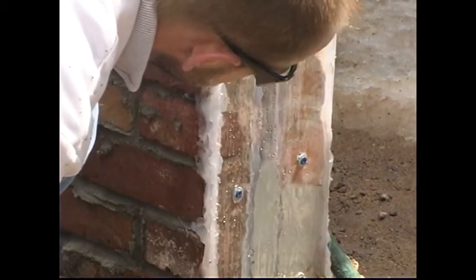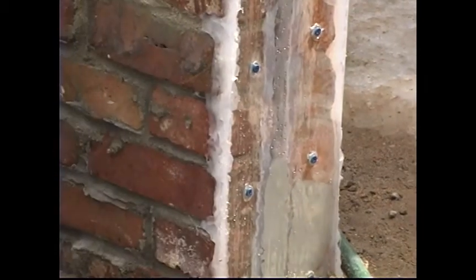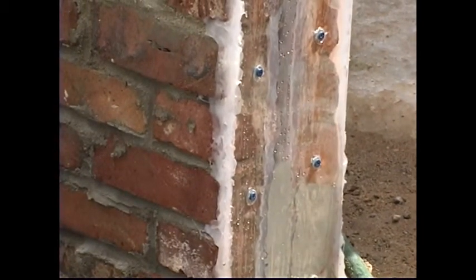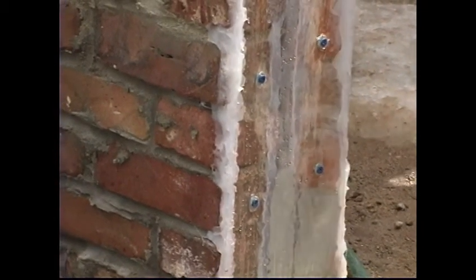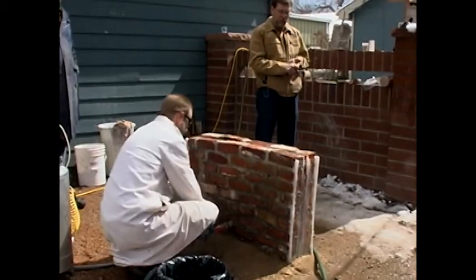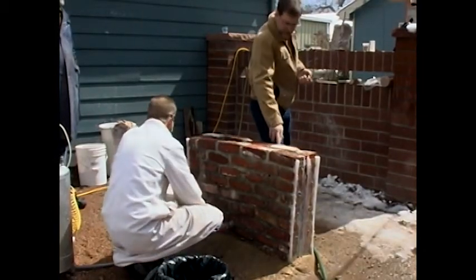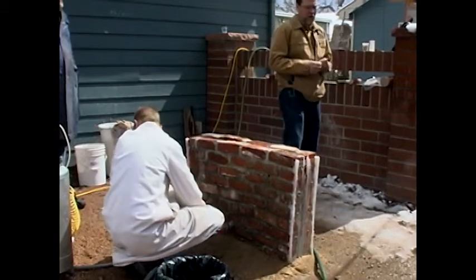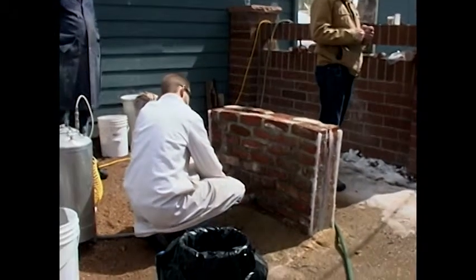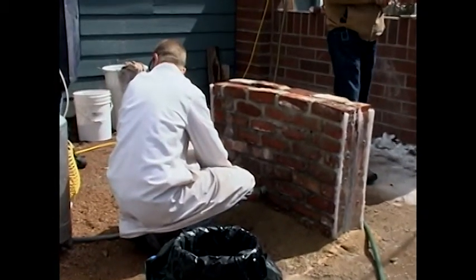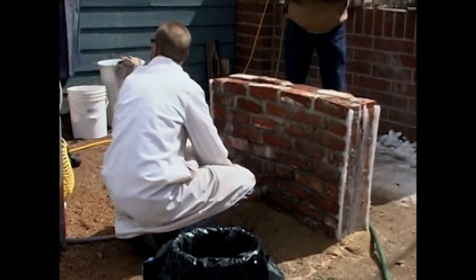So usually, the injection process starts with some of the investigative work that you saw. It's our job to figure out how often to put the injection ports. There is some pointing work involved. I mean, this material flows really well. So if there's cracks, generally with a material like this, if we have a crack wider than 1/16 to 1/8 of an inch range, they've got to point it up, or else the material will flow out of there.